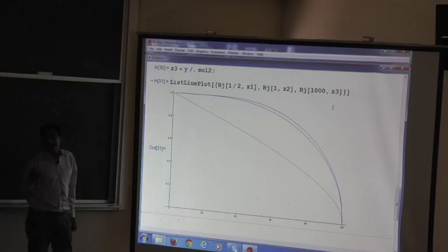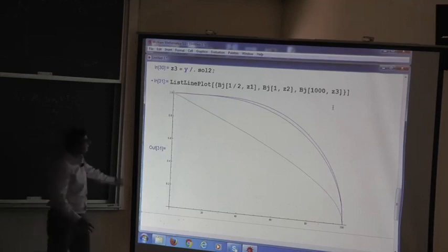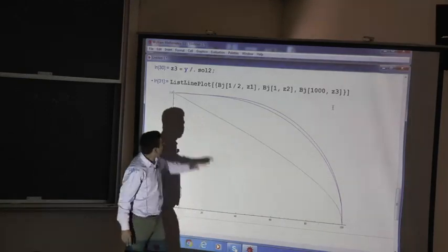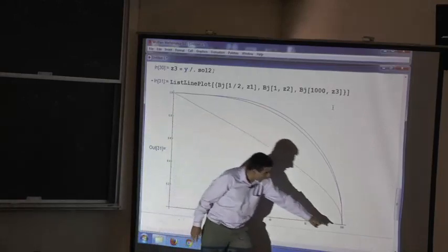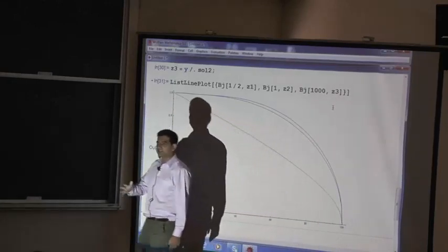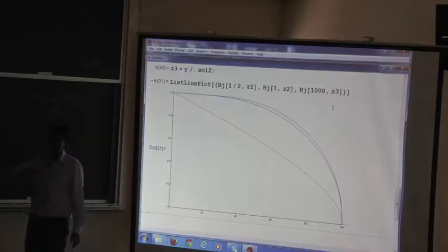For 3d elements, it's easy. My J is equal to the S, so I can just look at the spin of the ion because the orbital angular momentum is quenched. For 4f ions, however, I have to take the overall J. But this is the general behavior. The magnetization drops as the temperature goes up, and there's a phase transition here at which the magnetization goes to 0. Now the magnetization of a paramagnet beyond the Curie point is minuscule compared to the magnetization of the ferromagnet, so it can be taken to be 0 on this scale.